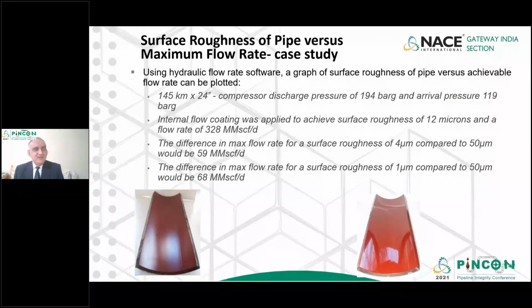So there is one company in South America called Gas Atacama. What they did is they took two pipelines of identical diameter and wall thickness for hydrocarbon gas, like natural gas pipelines. And they applied different kinds of available flow coating materials, some with a very high volume solid and some with normal moderate volume solid. They did the calculation and came up with the criterion that the higher volume solid product, which gives a smoother surface, where the smoothness can be measured in terms of RZ value, gives a better advantage in saving on pumping cost.